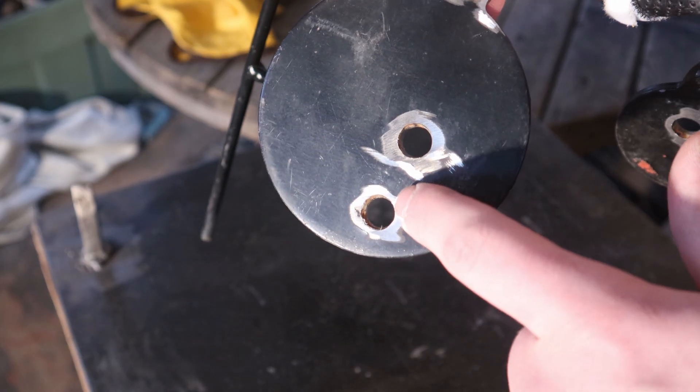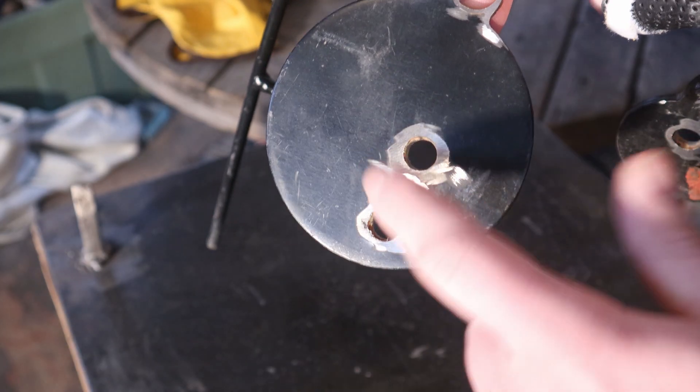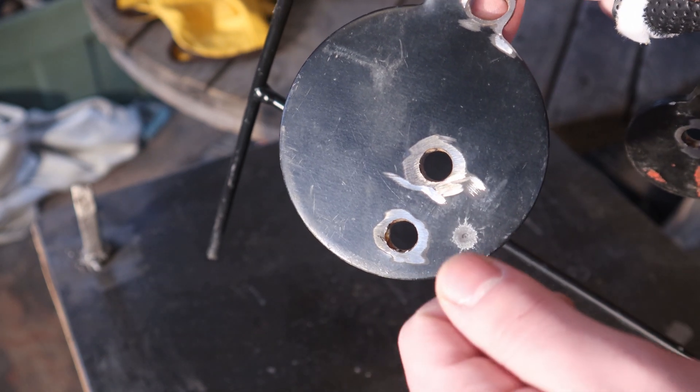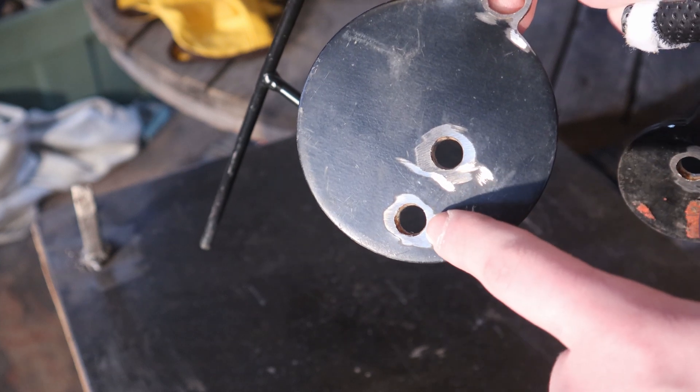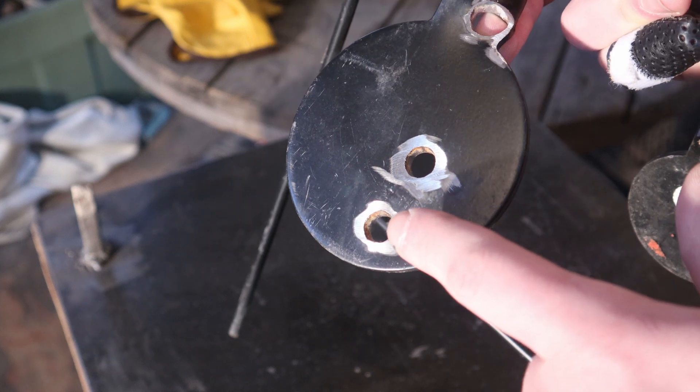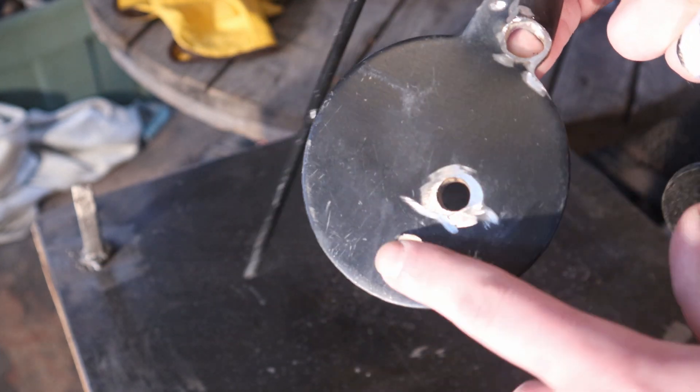Then I'll flip it over, and because the backside will be completely filled, I will weld in a big circle. So I'm melting the entire diameter of the hole and keep adding filler rod to that quickly so that I fill the hole full of material past its surface level. And then we'll come back with a grinder and grind off both sides so they're flush with the material.